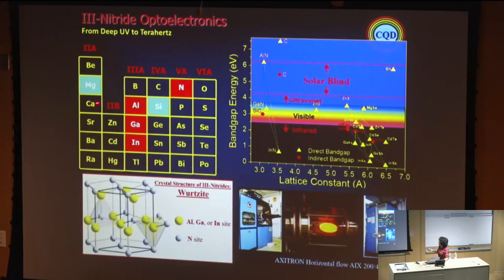So here we can see that aluminum nitride has a wide band gap, 6.2 electron volt, 200 nanometer, and by doing band gap engineering, coming to gallium nitride, you can make devices that cover the solar blind band, ultraviolet, visible, and infrared, and at the same time, with the intersubband, you can go even up to terahertz. But our objective for the moment is here. There is a big problem because these III-nitrides, as they have large energy gap, have direct energy gap, but they have wurtzite symmetry crystals, and it's very hard to make them p-type conductivity.